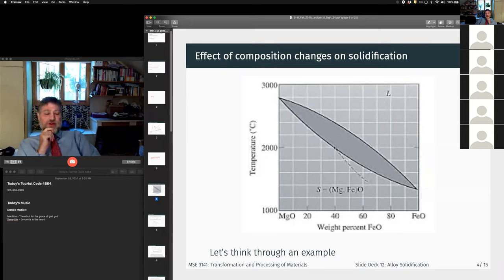In a pure material, we have a single melting point, and all of our previous discussion was about that melting point. Here we have a range of temperatures, but we also have a range of compositions. If we come down and we're at 40% iron oxide, 60% magnesium oxide, the first solid that's going to form has a composition of slightly less than 20% iron oxide, while the liquid is still at 40%. And then the last solid to form is going to be at 40% iron oxide, but the last liquid that freezes out is going to be way over here at 65% iron oxide, right?